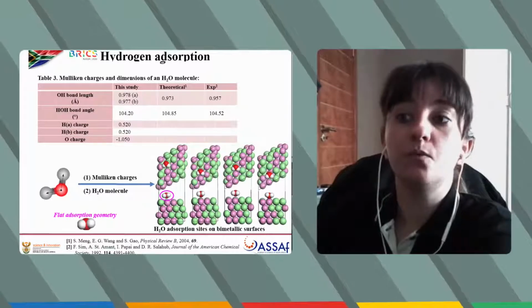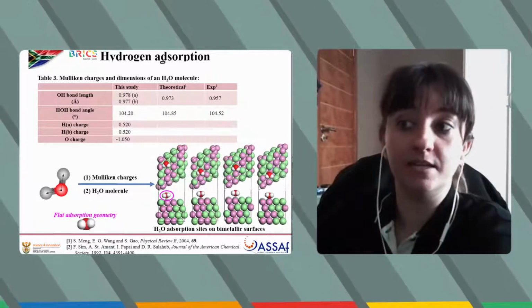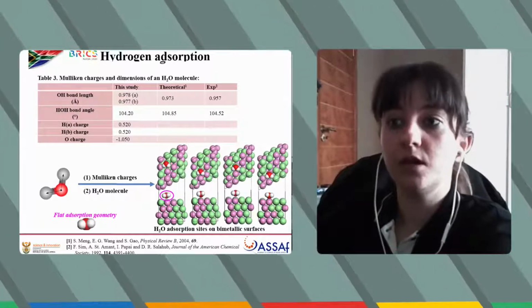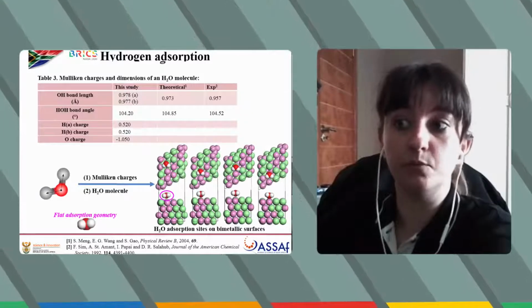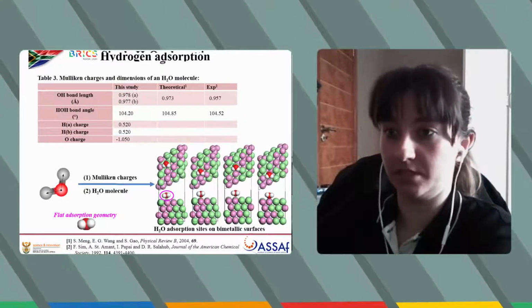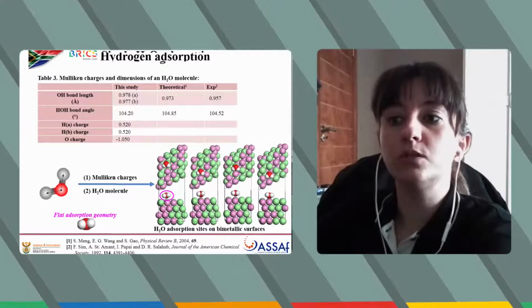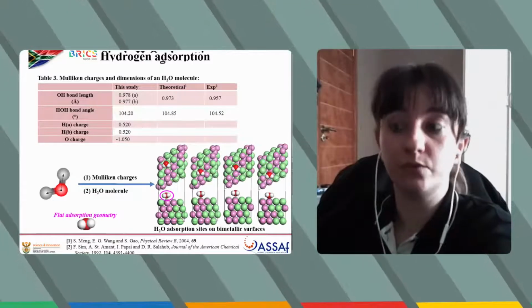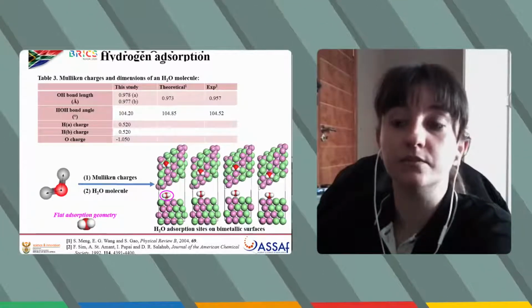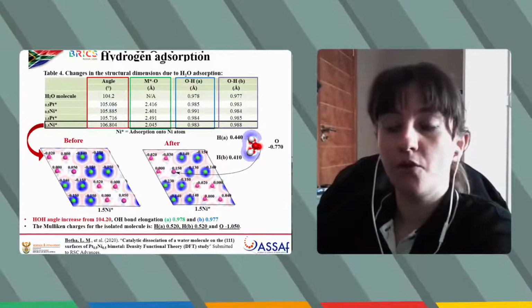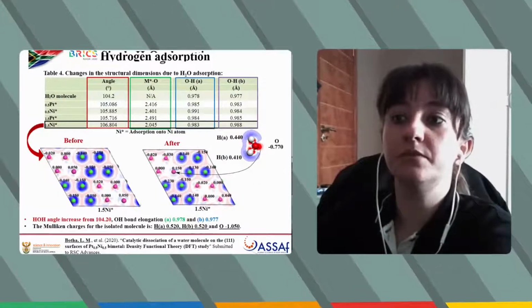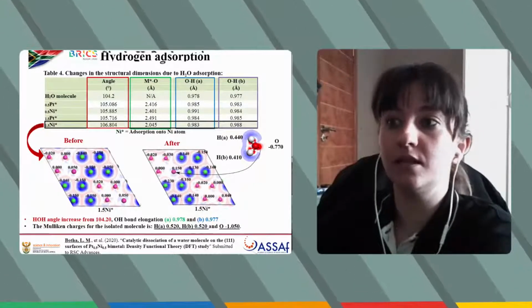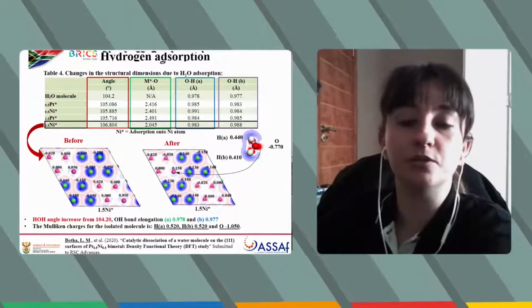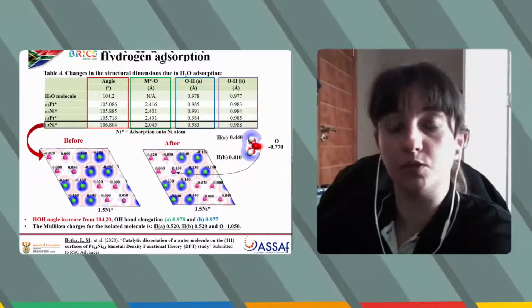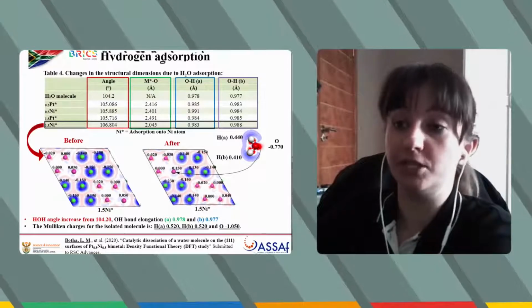An isolated single water molecule was validated before absorption. As seen from the values in the table, the model is sufficient for absorption investigations. A single water molecule was absorbed in a flat orientation onto the bimetallic surface. From table 4, it was observed that the angle and the bond lengths increased as compared to the dimensions of the isolated water molecule, indicating dissociation.